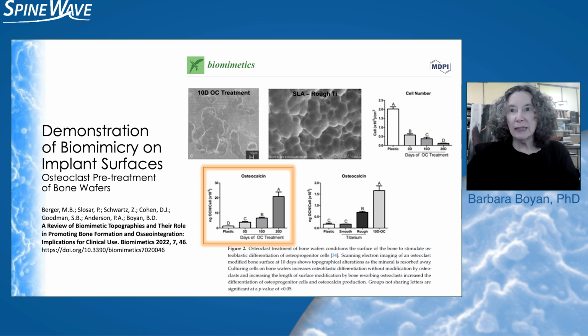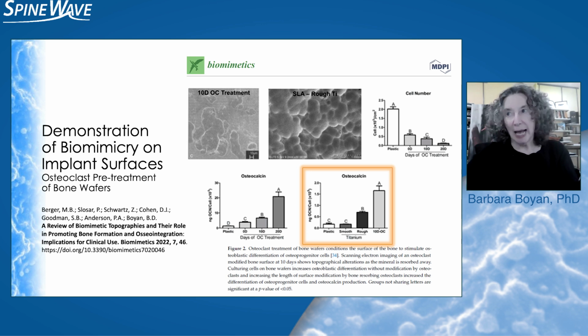And now we want to see, did we recapitulate with the osteoclasts anything that was similar to what was happening on the titanium surface? And here is machined titanium, which behaves very similar to plastic. We make that surface rough, like this picture here, but still, when it's an osteoclast resorbed surface, they behave much more like fully differentiated, very happy osteoblasts, and they are producing a whole lot of osteocalcin. So what is it about that osteoclast surface that is so special? And that's really what we're trying to now recapitulate in a material.